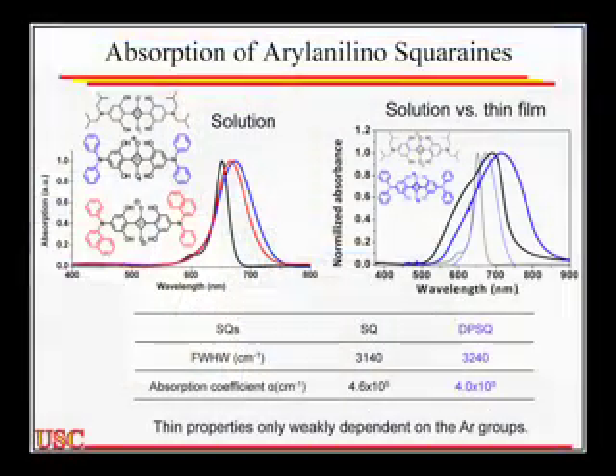Another big benefit from these: these are the solution spectra for my parent squaraine, which is the isobutyl derivative. The diphenyl is in blue and the phenylnaphthyl is in red. Remember I said I wanted broad lines? Look at those. We're double the width, and this is in solution. Remember, my normal squaraine more than doubled in line width when I went from solution into the thin film. So if these more than double in line width, I'm going to be way out here somewhere. That was what we were hoping, not what we observed.